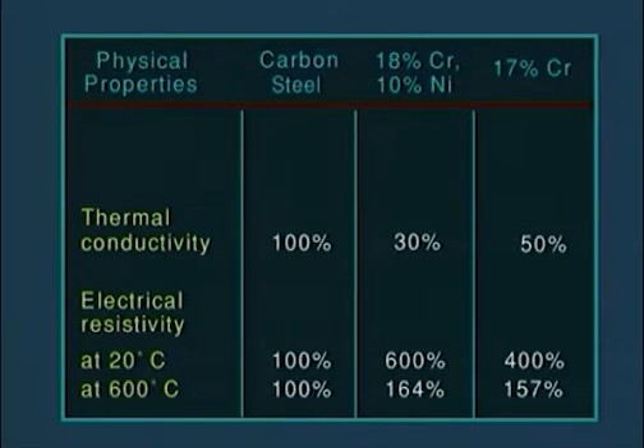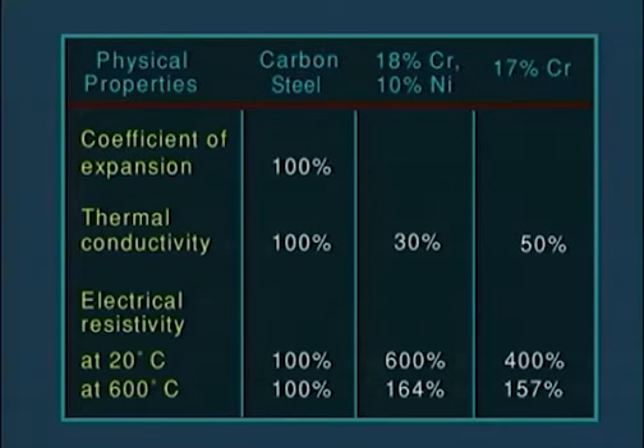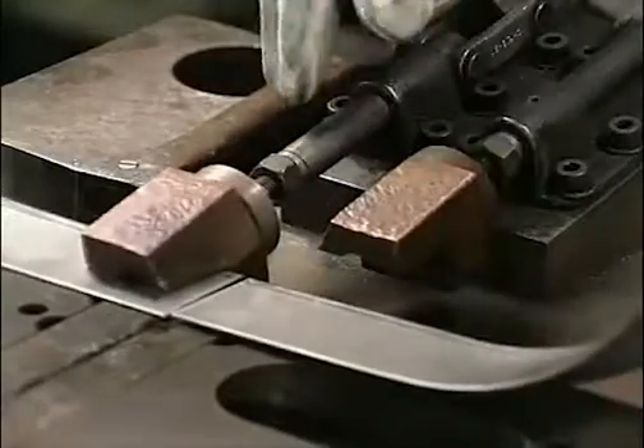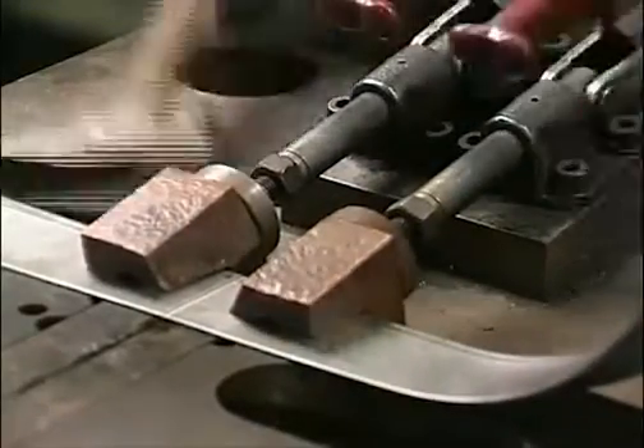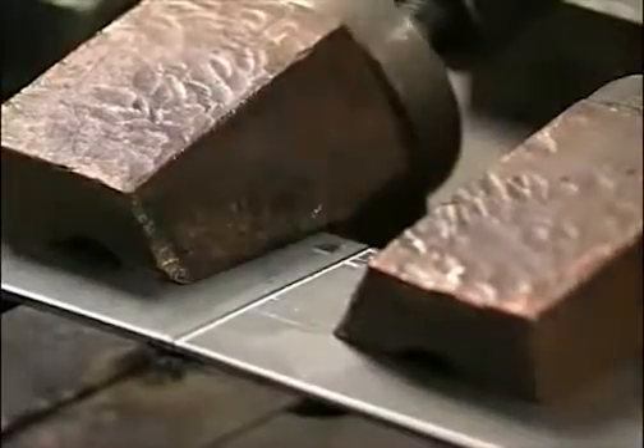However, their lower thermal conductivity means that a steeper temperature gradient will be formed. This, combined with their higher coefficient of expansion, generates larger stresses, and so austenitic steels tend to distort more during welding. It is therefore essential that welds are jigged securely, and if possible, hard chromium-plated copper or aluminium backing bars should be used to conduct heat away from the weld area.